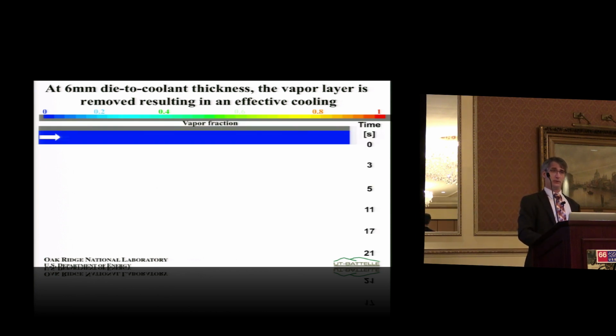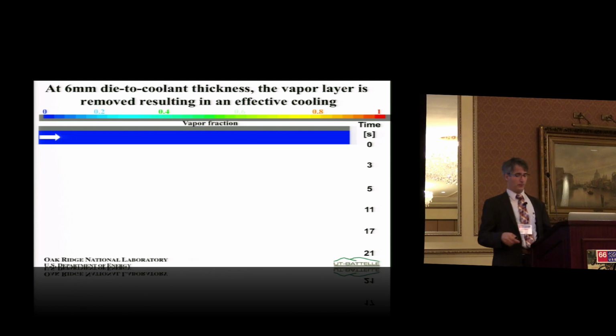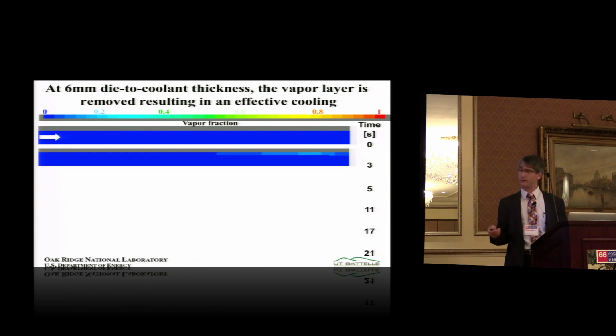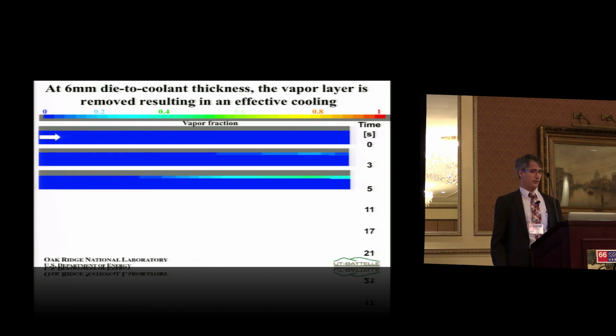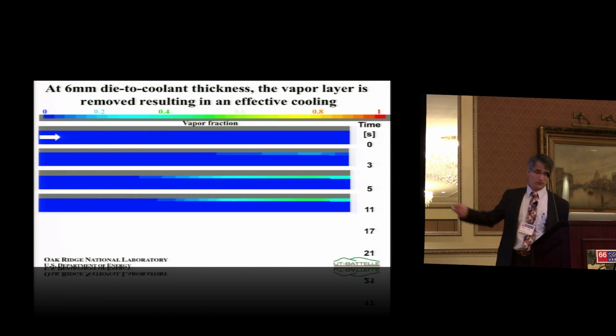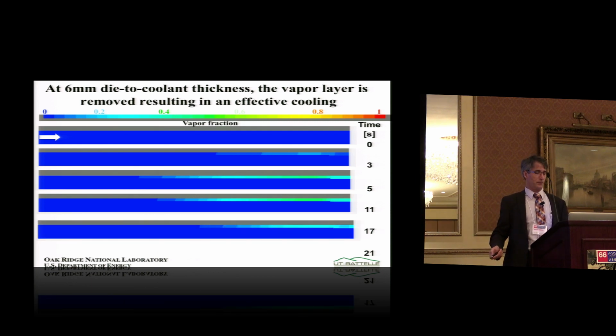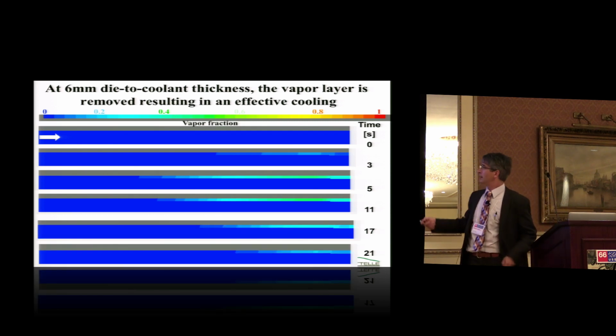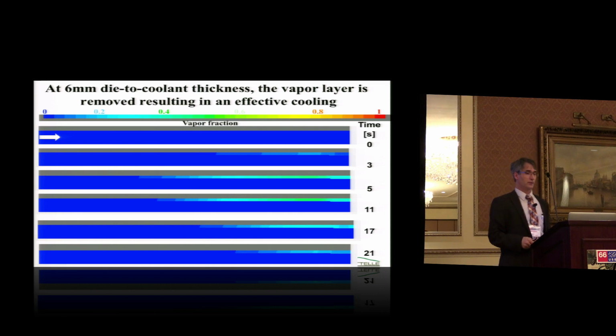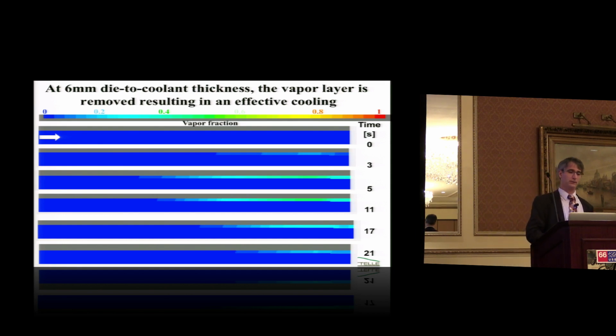So initially, there's no vapors because it turns out that the fluid has actually carried out that top layer. You see how it forms? So it's interesting. It proceeds like that. You have a liquid layer confined on vapor layer confined on the top of the channel, and gets convected away as the cycle proceeds. And this is a very good example. That's what we would like to see in our designs. So we identified at least one design that is going to work.